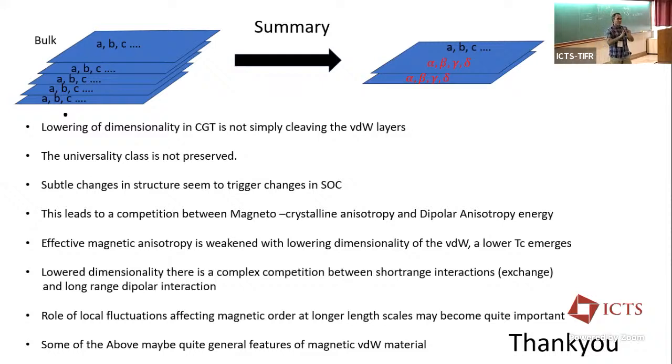As far as till now, we have not seen any possibility of antiferromagnetic correlations developing around the 14 Kelvin transition. So it's just that there is a strong loss in anisotropy, and the system, because of developing shape anisotropy, pushes the magnetization in plane, and that's where you see the magnetization starts turning around. Okay, so is that a crossover or a phase transition? It's a critical crossover, because you go from one universality class which is sitting at 67 Kelvin to one which is at 14 Kelvin, which is a completely different universality class.